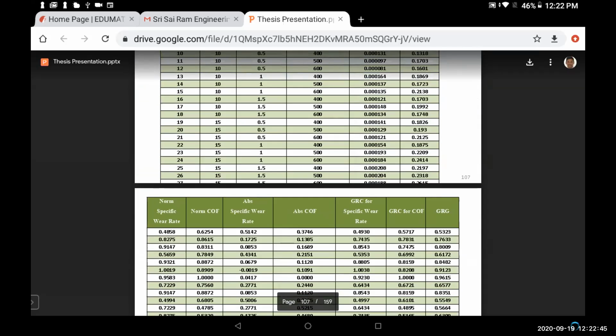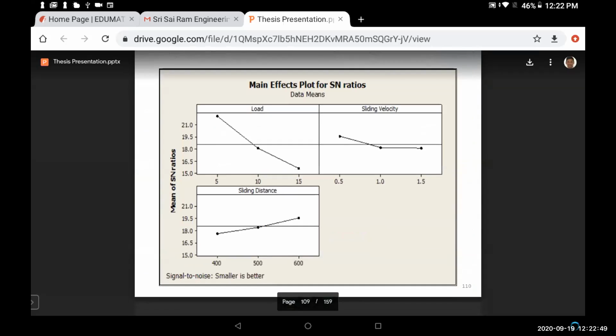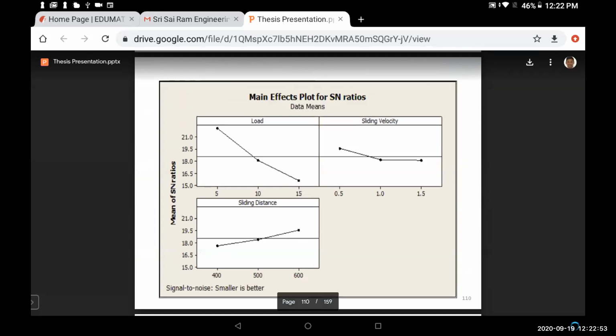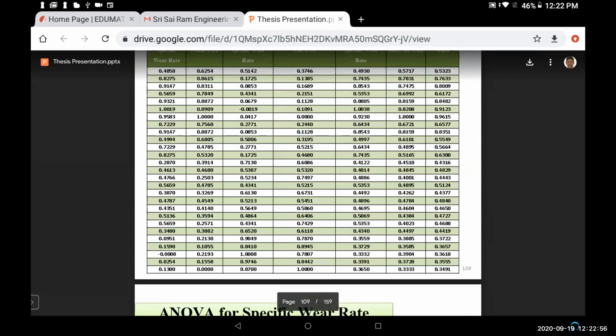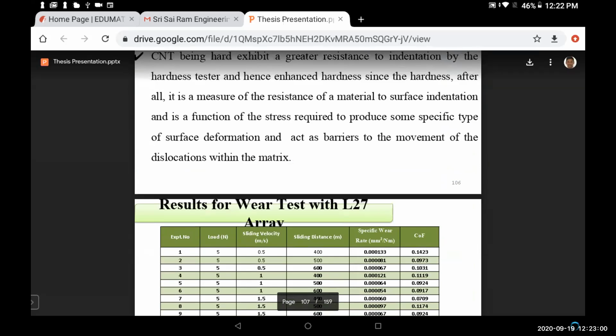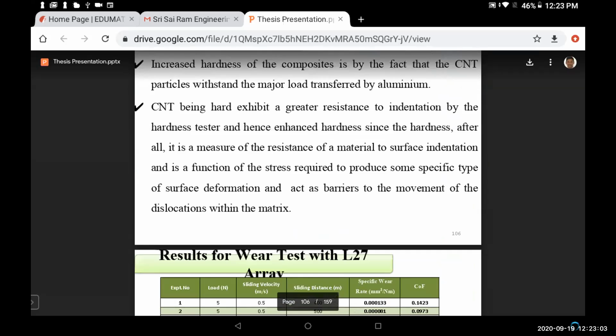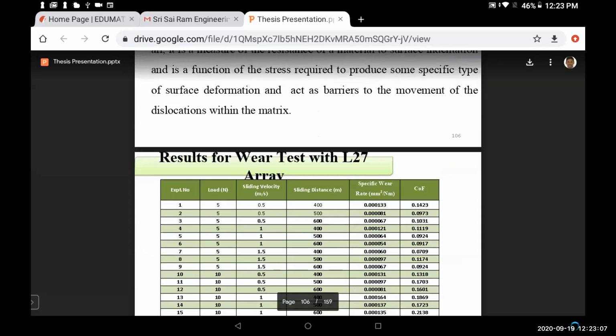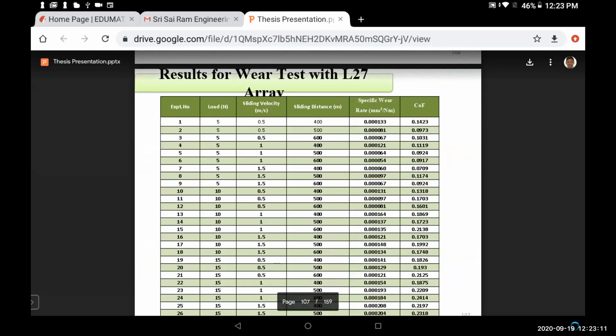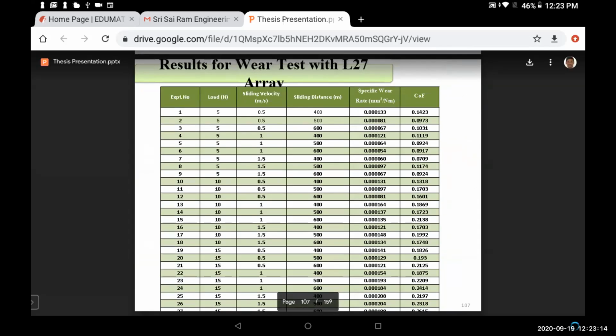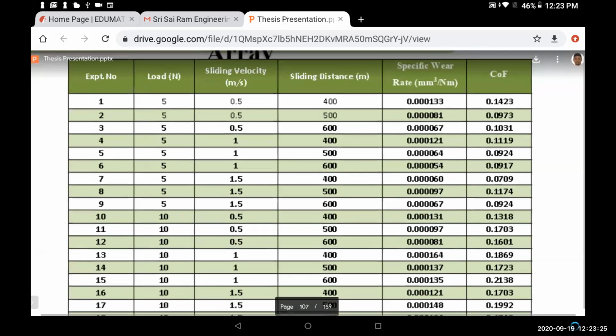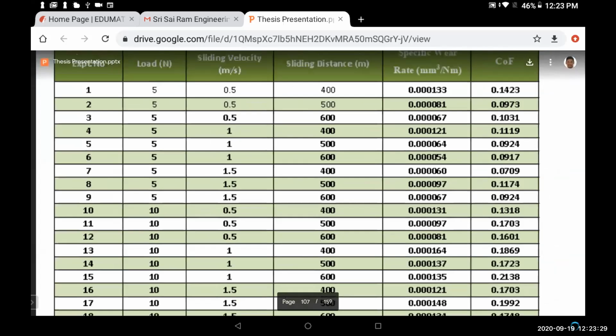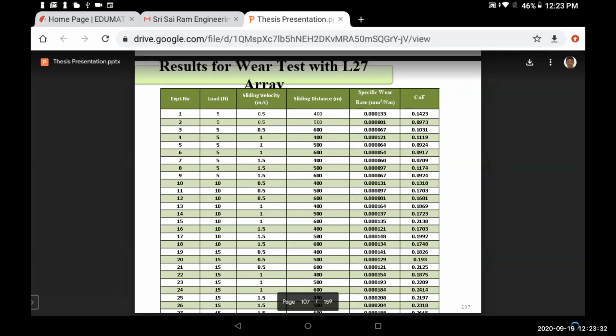Okay. So in order to analyze the wear of the material, the above four examples showed we started with a material with very good mechanical property. That mechanical property was mainly set for performing the wear analysis. So we performed L27, nothing but the orthogonal array, L27 experiments conducted by the variation of the load, sliding velocity, and sliding distance. These three are input parameters, as you see in this table, at three levels. So we got around 27 experiments. We calculated the specific wear rate as well as the coefficient of friction.